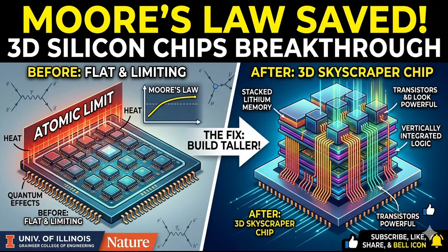The researchers also redesigned the transistors themselves. Conventional transistor fabrication often relies on doping processes that require temperatures above 600 degrees Celsius. To avoid this problem, the team used a design known as a junctionless transistor. Instead of creating complex doped regions after fabrication, the silicon is uniformly doped beforehand. The ultra-thin silicon layers still allow precise electrical control while maintaining strong performance and avoiding high-temperature processing steps. Using this approach, the team successfully built 3 stacked layers of silicon electronics, each containing 625 transistors. The results were remarkable. Manufacturing yields reached between 98 and 100%, indicating exceptional reliability.